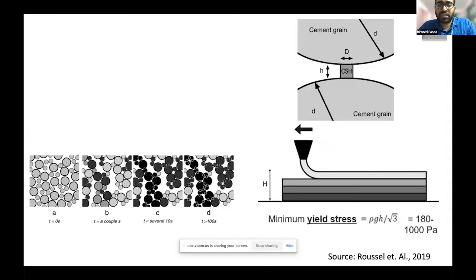And in this regard, when you are going for large scale printing, such as when you want to print an entire home, then of course we need to take into account the structural build-up of the material. If that is poor, then definitely after printing a few layers, you are going to end up with structures which are going to collapse very soon. On the other hand, if you have a material with a very high structural build-up rate, then you are going to end up with poor interlayer bond strength. So it means that if we want to promote such a technology, we must have a proper material science background so that we can develop a proper material for such technology.